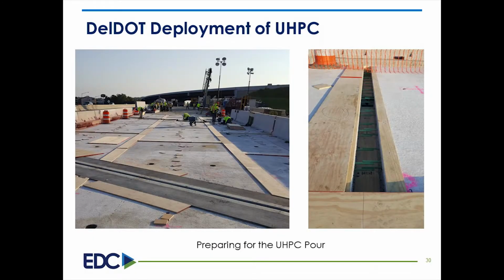So here's some of the pictures of it going on. Once again, we did have a really good contractor on here. He helped work through some problems. We had tolerance issues on our precast slabs, but because you've got a 4 to 8 inch joint there, you got enough room to take up some of the tolerance differences. And because we were putting in an overlay, if they weren't exactly level, it wasn't a big deal because we were going to grind it down and put an overlay on it anyway. But this was preparing for the pour.